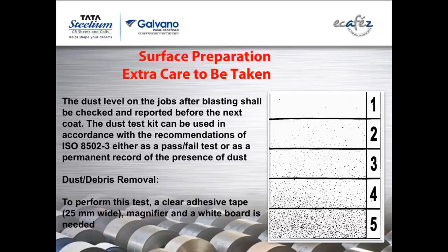Now again, in certain standards, customer specifications rather, they will say that it should not be more than 2. So if it is 3, 4 or 5, you either have to vacuum clean it or you will have to air blow and remove it. But this is coming out of your media. So better clean the media or filter the media so that this dust will not trouble you.